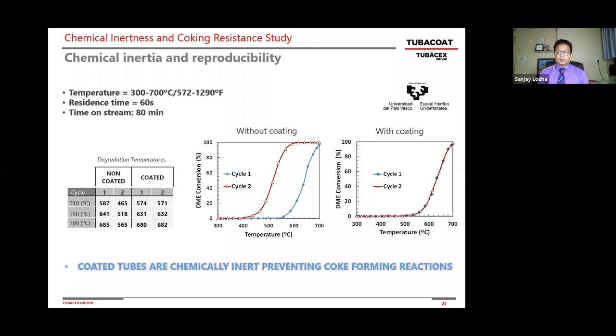But when you do that with the same substrate but the coated tube, on cycle one and cycle two, what you see here is no difference in startup run T10 temperature, T50 and T90, almost identical, which proves that the coated tubes, which are chemically inert, prevent or minimize the coke forming reaction when you go through multiple cycles, where the active metal does take part in promoting carbon formation. Next slide.